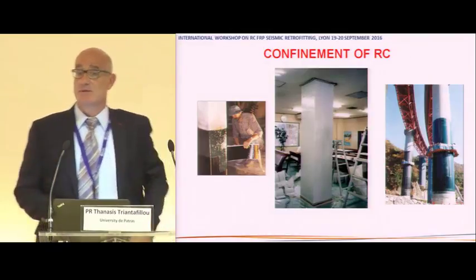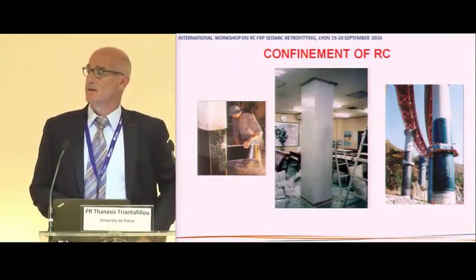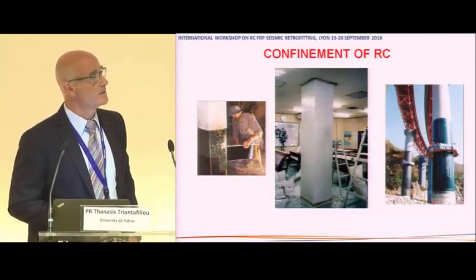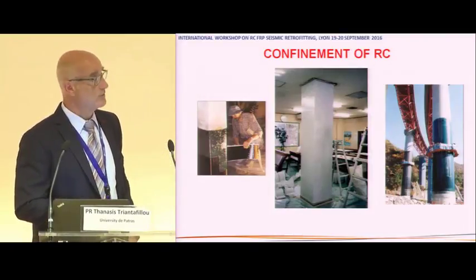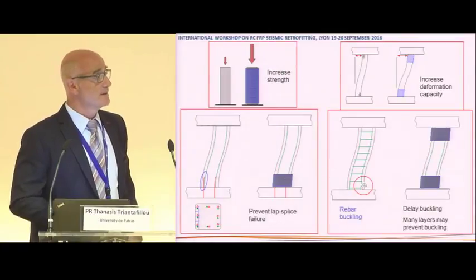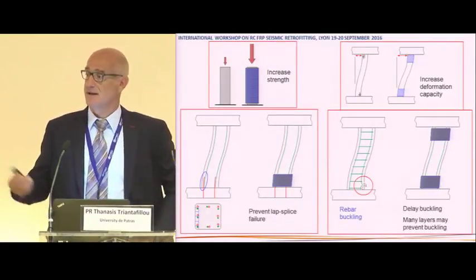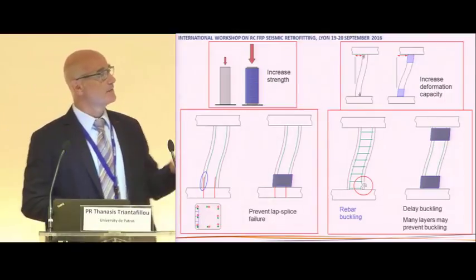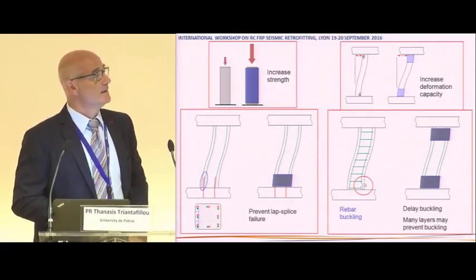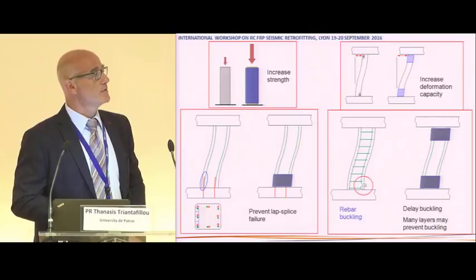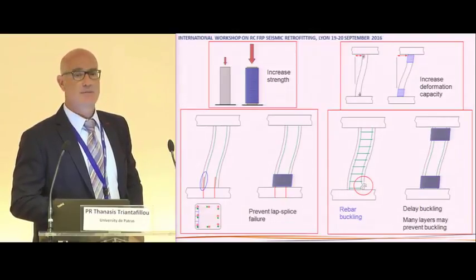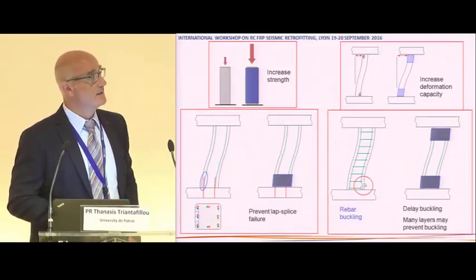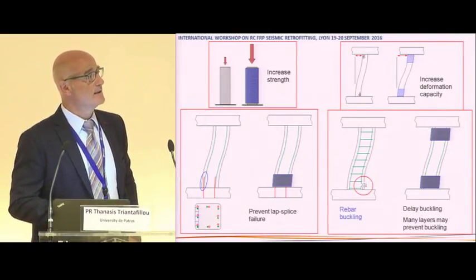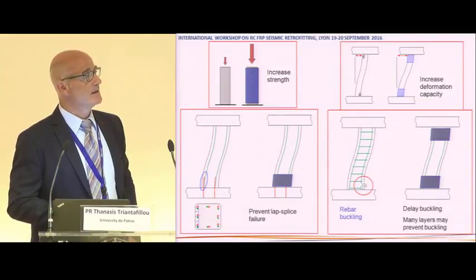Time to say a few things about confinement, which is probably the most important application of FRPs in seismic retrofitting. We do confinement for many reasons. They were discussed by Maurizio. I have tried to summarize them here as well. If we do full wrapping of columns, we normally do this to increase the axial capacity of members. But if our interest is increasing the deformation capacity, we only need to do local jacketing, only at the ends of members to confine those areas.